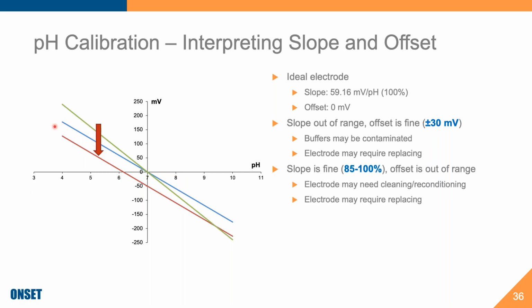Here we have the slope that's fine. It's actually perfect. It's parallel to the perfect electrode. But the offset is way out of range. It's negative 50 millivolts. So this definitely needs cleaning or reconditioning. And it's also possible that it's cracked, because in the end, potentiometric electrodes will always read a potential even if it's cracked, even if there isn't an electrode attached.